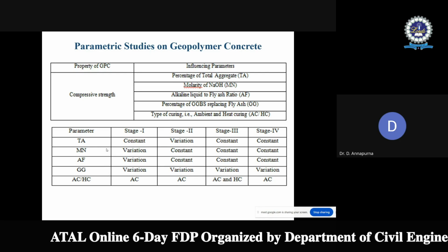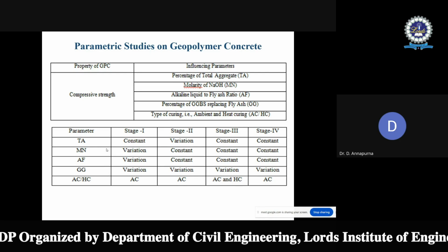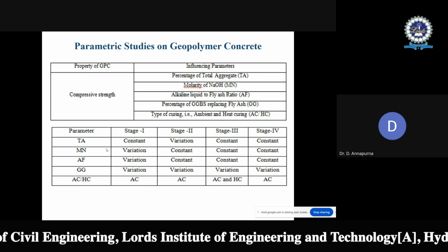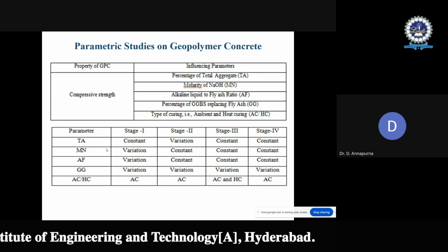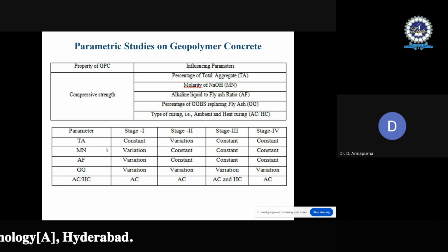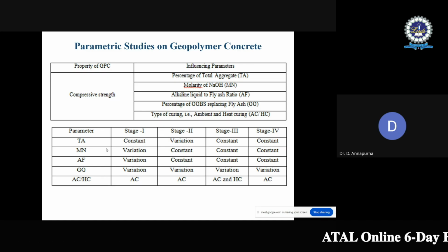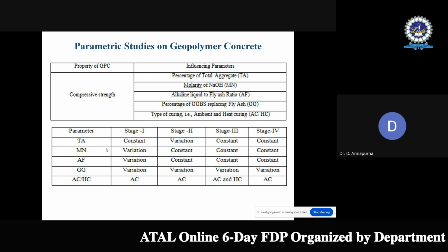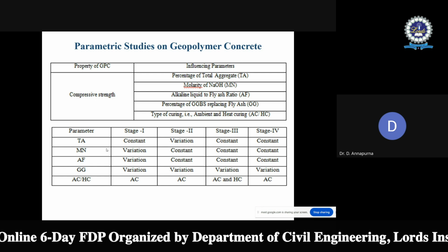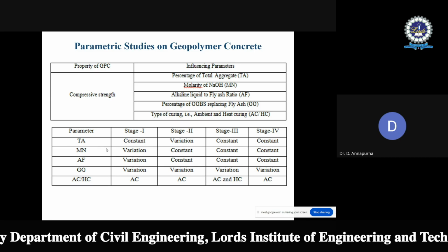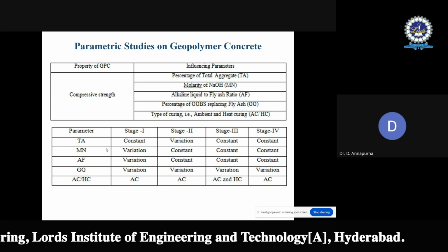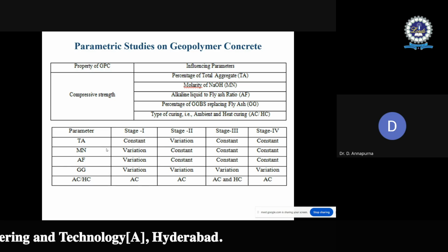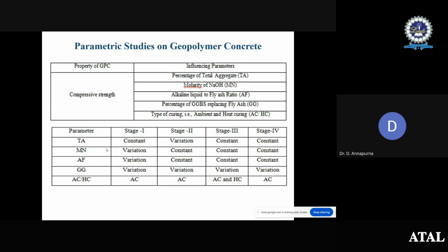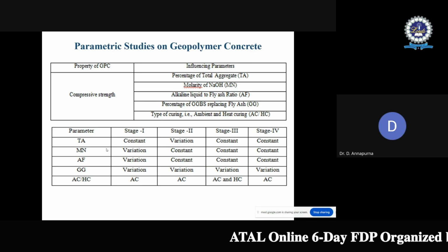Now you will be surprised why at all a 0.7 alkaline liquid to binder ratio is considered. Because when the research is looked back, the guidelines given by Rangan or other researchers tried using this alkaline liquid to fly ash ratio between 0.3 to 0.5, or some of the researchers went up to 0.6, or even 0.65. So that is the reason in this particular work, 3 different variations of alkaline liquid to fly ash ratios are considered as 0.3, 0.5, 0.7.